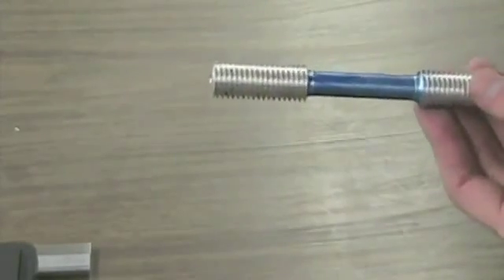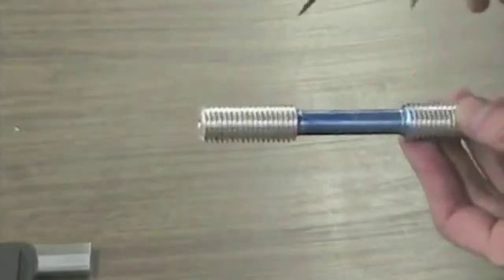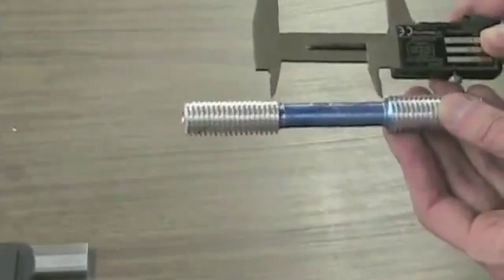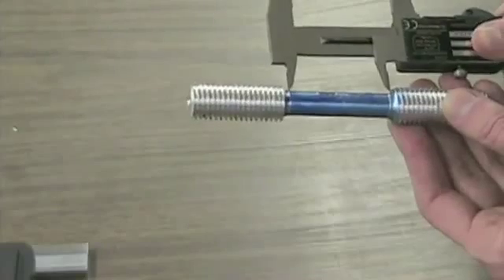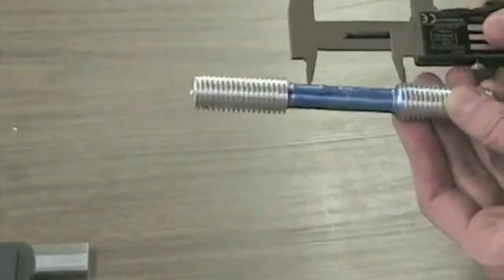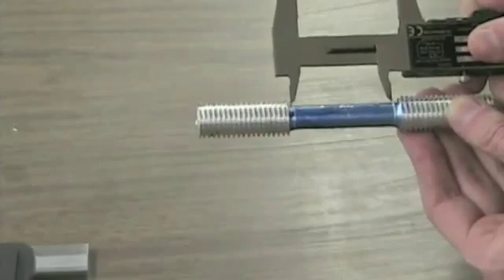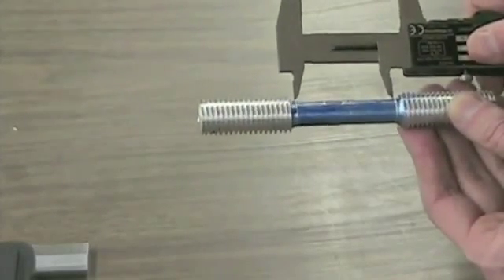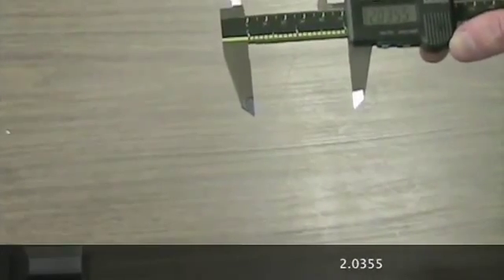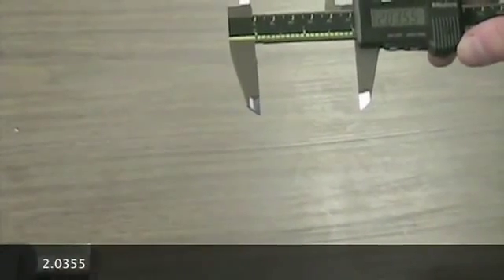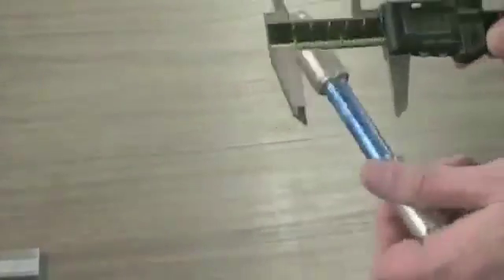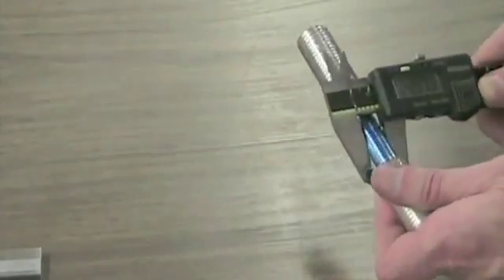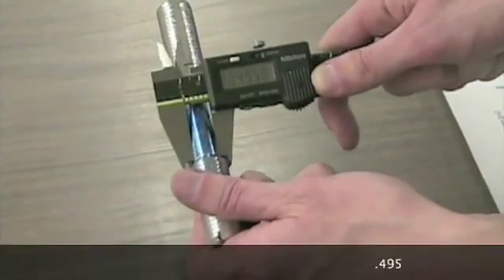We're also going to want to take our pre-test punch length, which is lines that we scribed earlier, so from here to here. Now I find it easier to measure it from the reverse end of a caliper for this part. Right there we have it at 2.0355. We're also going to want to take our measurement of the diameter. And right there we have it at 0.495.